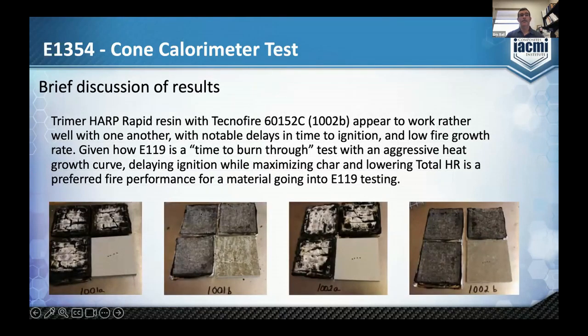So here you can see on the bottom these photographs. The second one from the left, and the fourth one, had the Tecnofire, and you can see that that's an intumescent, and it really provided a good thermal break as opposed to the ceramic materials. The ceramic materials kind of broke apart. That's the first and third one, and so going forward, we felt like the Tecnofire was going to do a better job at protecting the laminate going into the E119 test.